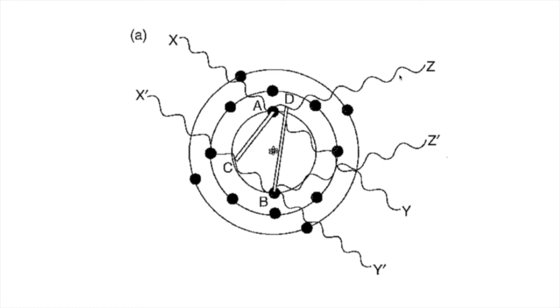Those cause a phase difference, and the net effect is destructive interference. So the intensity is going to be less than just the sum of all the intensities, because we have diffraction occurring amongst the individual X-ray beams interacting with different electrons at different positions.